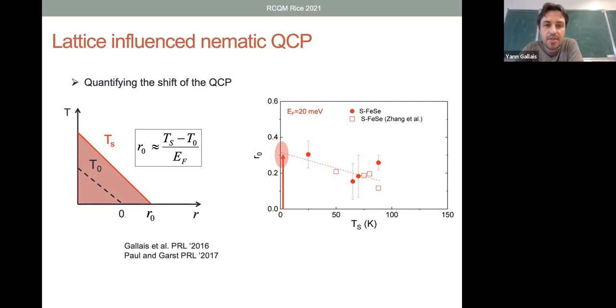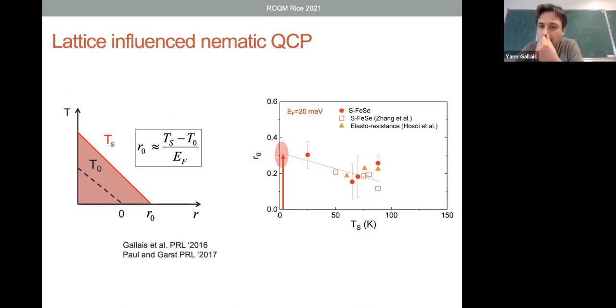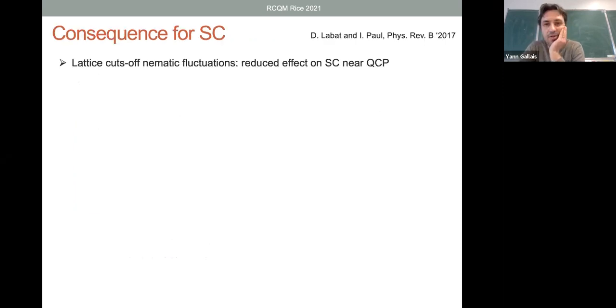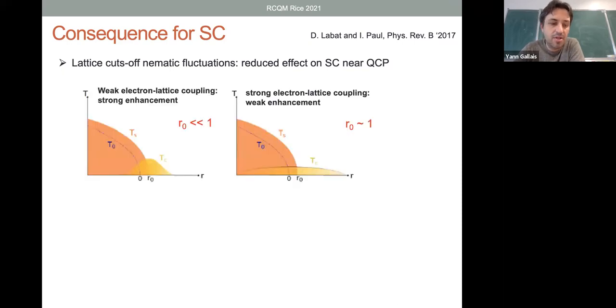Now, what is the consequence of this significant nemato-elastic coupling? This is work that was actually done by my colleague Rafael Fernandes. One of the main effects of this coupling is that it essentially cuts off the nematic fluctuations, and the consequence of this cutoff is that there is going to be a big impact on the superconducting pairing. What they found is that you have two regimes. One regime is where this R_0, this lattice shift, is small.